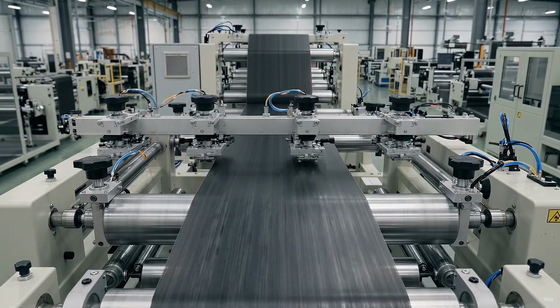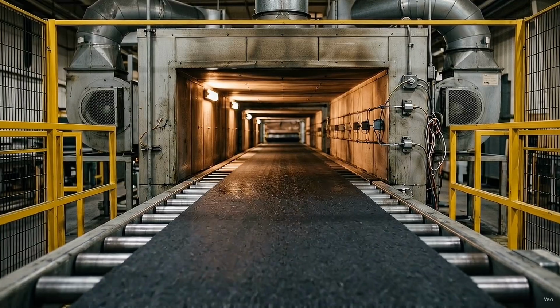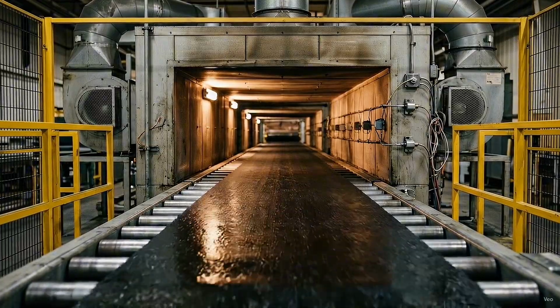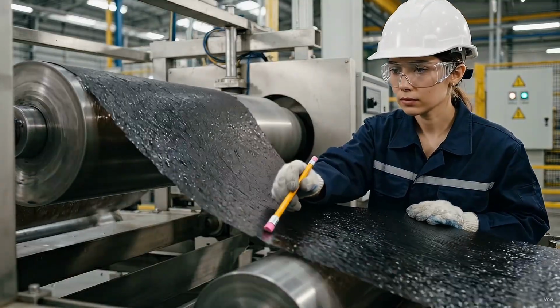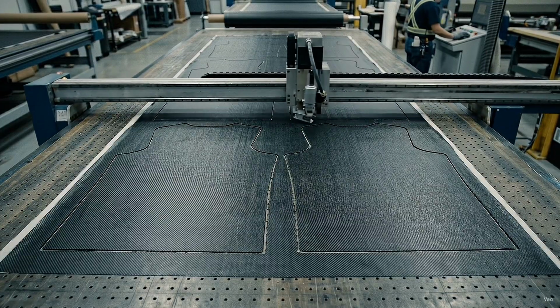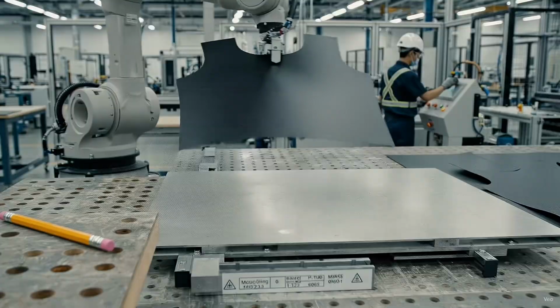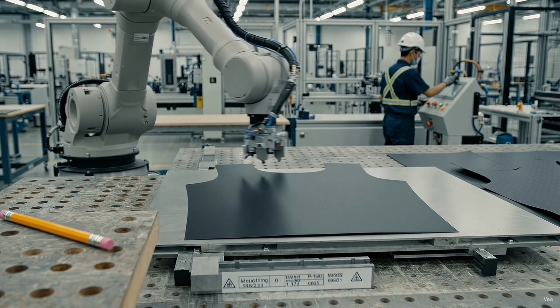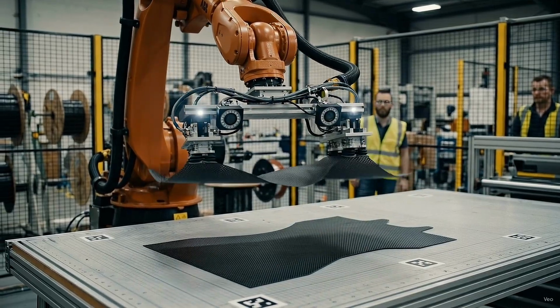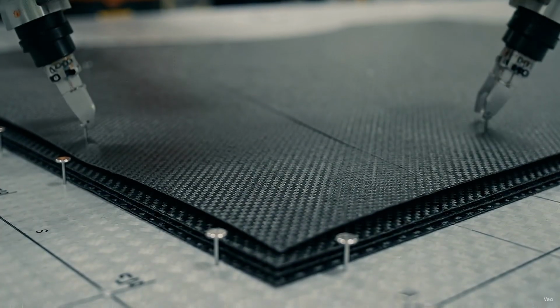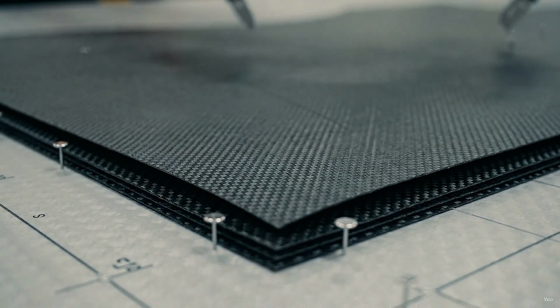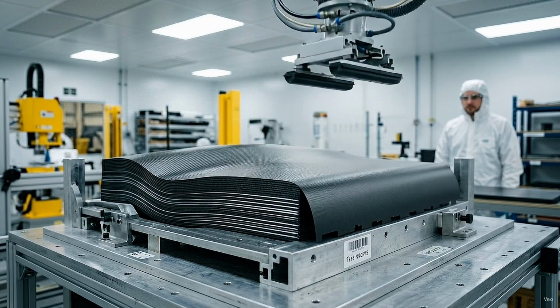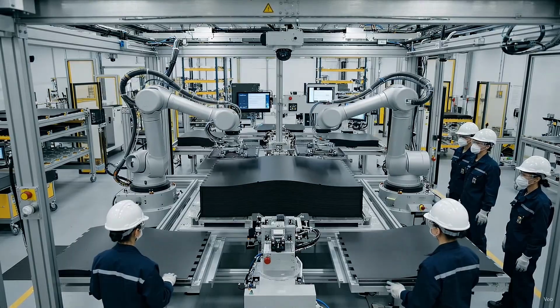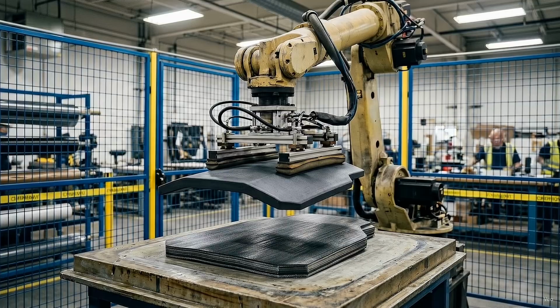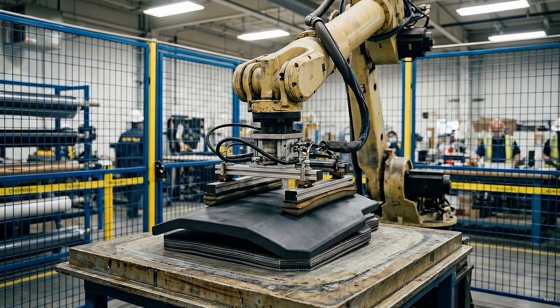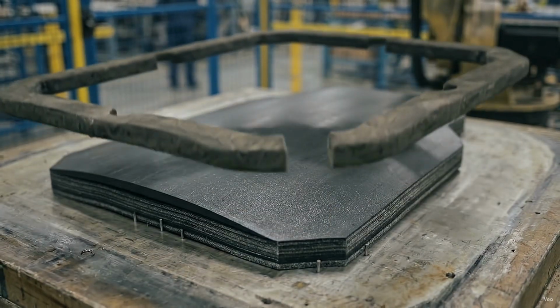The assembled preform would settle into a matched metal mold where guides preserve its shape and keep each layer in the correct position. A hydraulic press would apply controlled heat and pressure. Flowing resin would fill spaces between fibers and bond the components into one dense panel. Insufficient conditions can leave voids and weak interfaces, while excessive pressure or heat may remove too much resin or damage fibers. Sensors would track temperature, pressure, displacement, and time. Cooling channels would lower the mold temperature while pressure remained applied, reducing warping and locking the internal structure in place. The cycle record could later be linked to the plate.